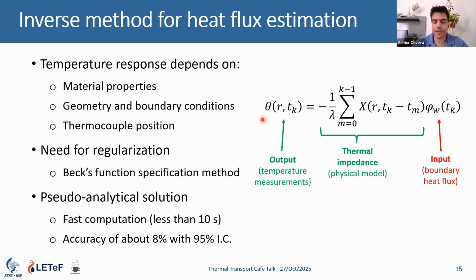As we are measuring the temperature, the thermocouple we are using can have a major influence on the heat flux estimation. Most studies regarding quenching know there is this effect from the thermocouple, but there is not much correction of this thermocouple signal.